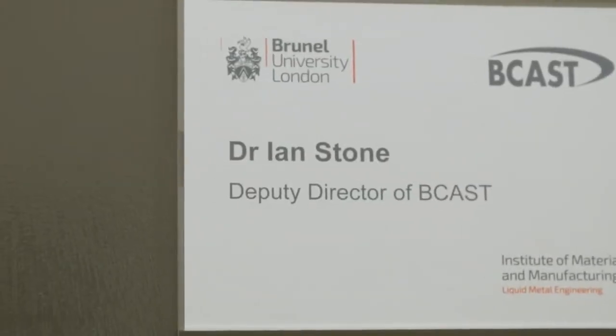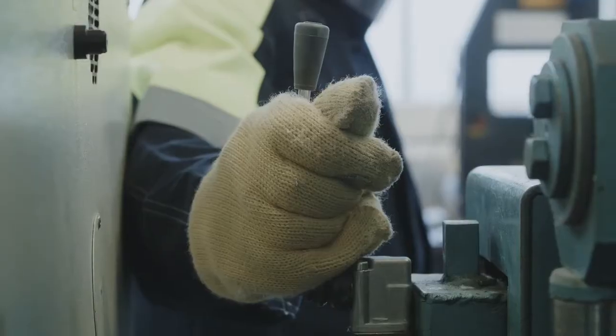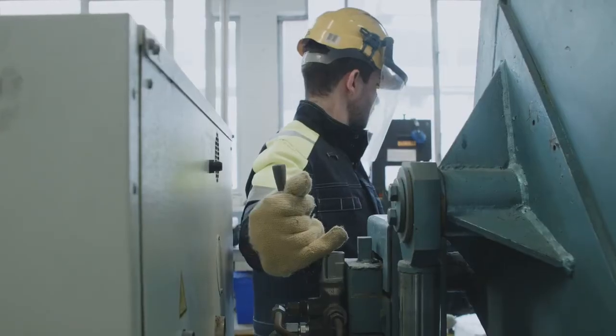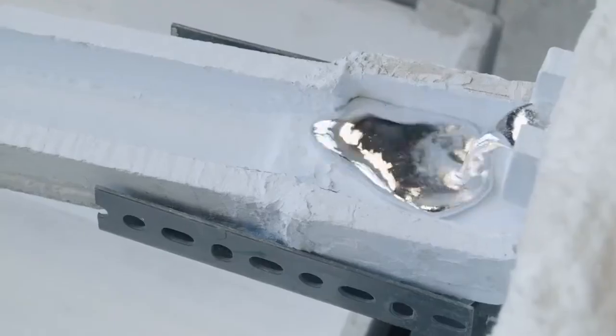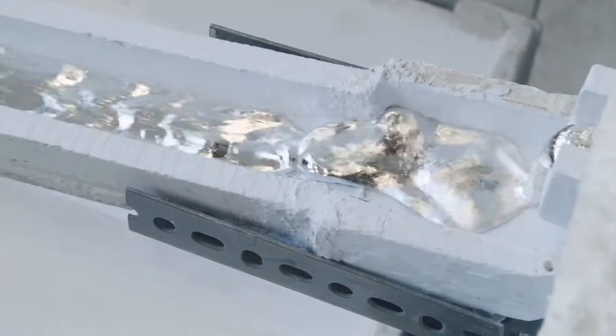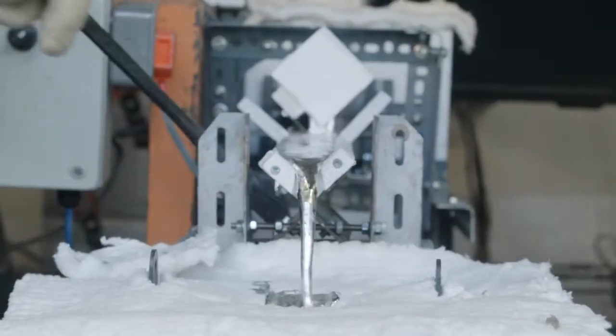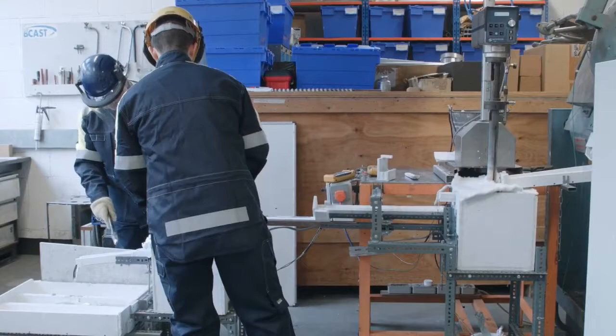Essentially, in our previous process, what we were doing is applying high shear forces, and they break up naturally occurring oxide films which float around inside the liquid metal. So all liquid metals have these oxide films floating around, and because they act as films, they essentially act as little cracks, and that makes the material very brittle. And so by breaking those oxide films up, you break them into little particles. Those particles are much more benign and they don't act as cracks, and that improves the quality of the metal.